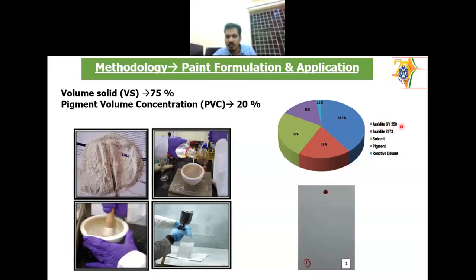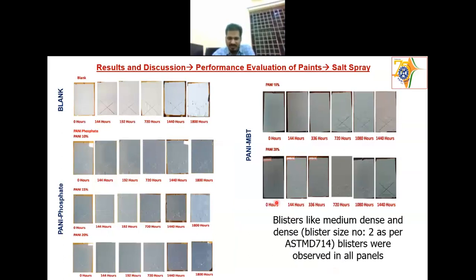So these are the different ingredients added here. Araldite GY 250 is the resin, and this is the hardener. It's an epoxy system, a two-pack epoxy system, 2:1 ratio. We mixed it, and the reaction happened, and then finally we got the coating. This is the coated sample. Then we did the salt spray testing and all those things, to find out the barrier property of the coating.